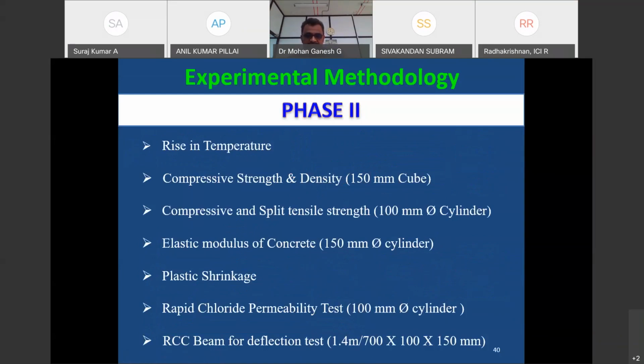Now, in the second phase, we have to do the detailed study. We have done rise in temperature, compressive strength and density for 150 mm cubes, compressive strength and split tensile strength for 100 mm cylinders, modulus of elasticity with the cylinder, plastic shrinkage, RCPT, and RCC beam with deflection test. Here, the size of the beam is 1.4 meter. Two types of beams we have done. The first set is 1.4 meter, the second set is 700 mm with 100 mm by 150 mm. This is the cross section.